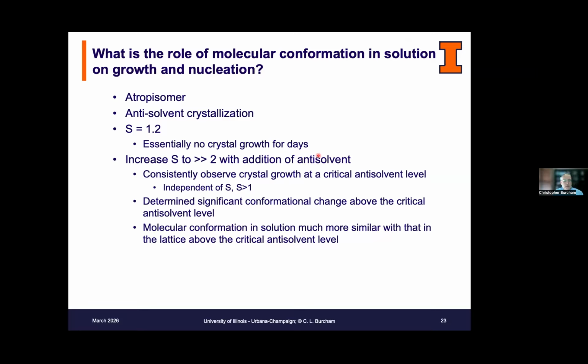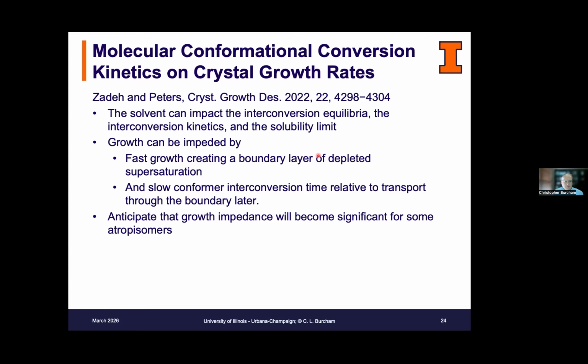What we determined is that it involved a conformational change of the molecule in solution. The addition of the anti-solvent changed the conformation of the molecule in solution and made it look like that of the lattice. And so we realized that there is something to be said for the impact of the conformation in solution relative to the conformation in the lattice, and the energy that the molecule must overcome in order to make that conformational change. This led to some work that Peter's group did, where he looked at the theoretical impact that this interconversion equilibrium can have and found that growth impedance will become significant for such atropisomers. Exactly the conditions where we saw that steric hindrance can interfere with the ability of the solute molecule to change its conformation and to attach into the lattice.